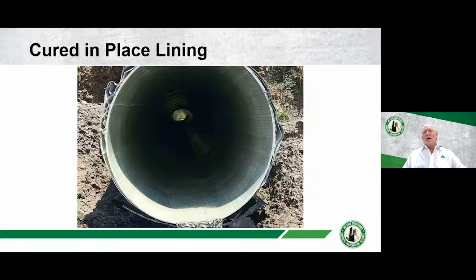The way these often work is that you've got basically a large sock. You take the sock, impregnate it with the resin that you're going to be using, pull it through the pipe, and then you actually inflate the sock using high pressure air, sometimes high pressure water, and get the sock up tight against the wall, and then allow that to cure. And what they'll end up with is a full polyester or vinyl ester liner on the inside of the culvert.